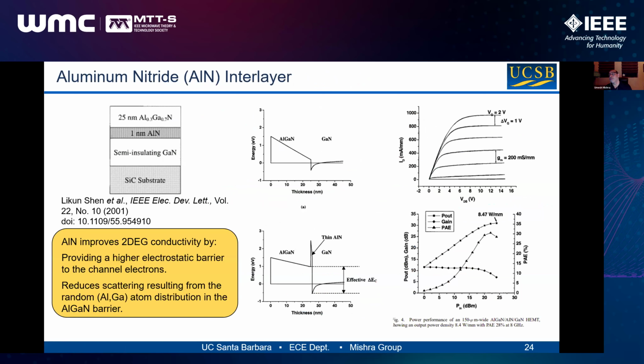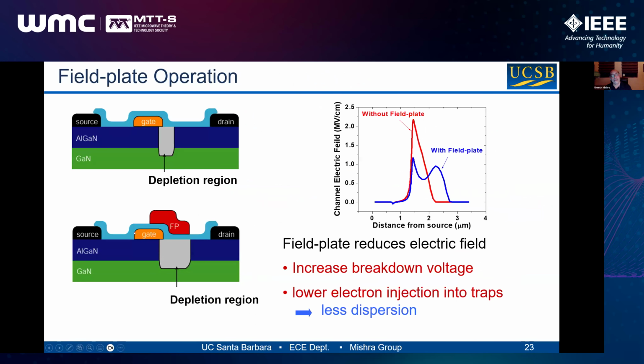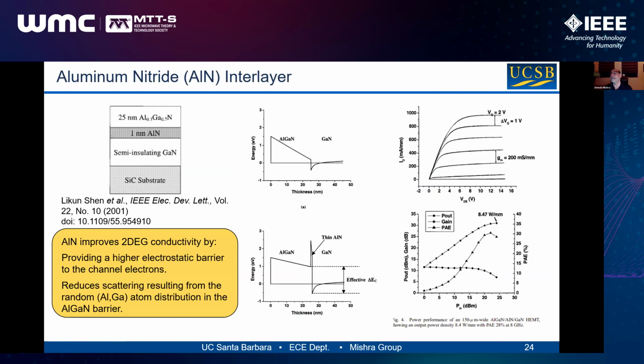So now, what were the big things that made this happen, right? One was the field plate. Like I said, here's a gate, and then Alessandro Chini and I, who's now in, I think, Modena, did this field plate, and then what we ended up doing is you could spread out the electric field, basically get the peak electric field down with a field plate, and then you could increase the voltage handling capability of the device. That's huge, because the big advantage of gallium nitride was the big band gap and therefore higher voltage.